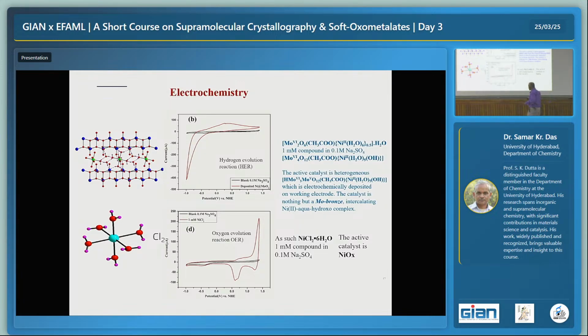By the logic of inorganic chemistry, what we explained when the reviewer asked, is that due to strong hydrogen bonding, the electron density around the nickel gets reduced. The electron density drifts from the metal side toward the hydrogen bonding. So the nickel center becomes electron hungry, prone to be reduced, isn't it? So that's why maybe it reduces easily from nickel 2 to nickel 1 and gives the hydrogen reaction.